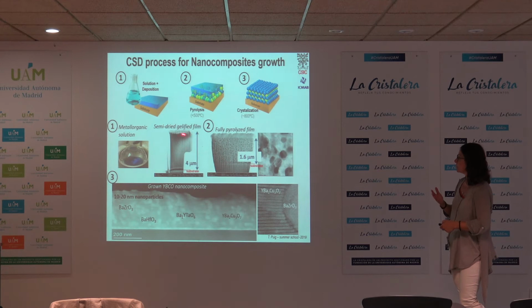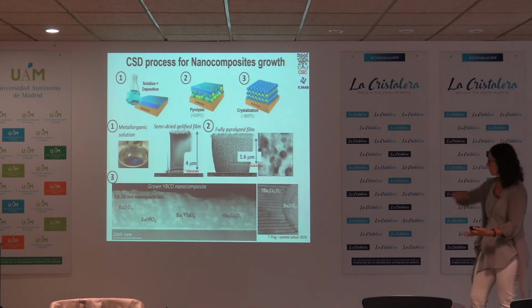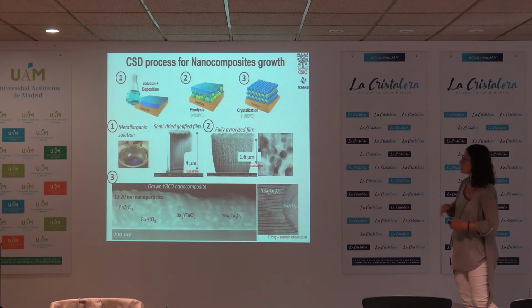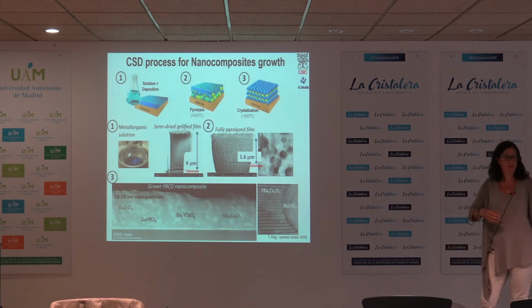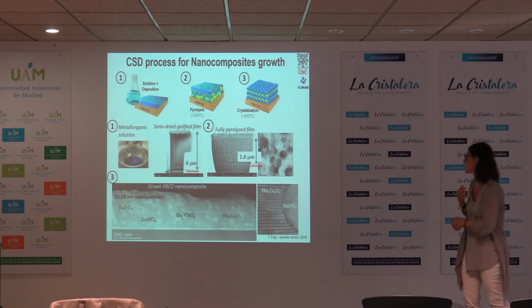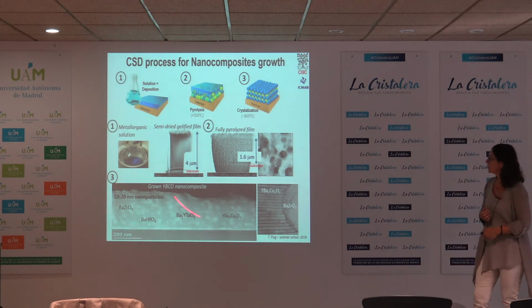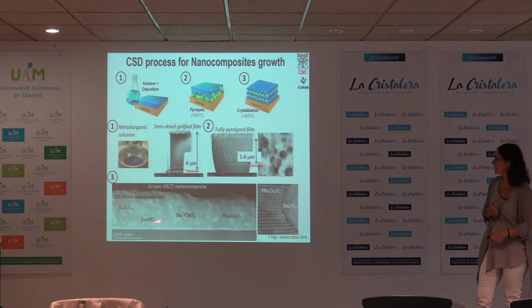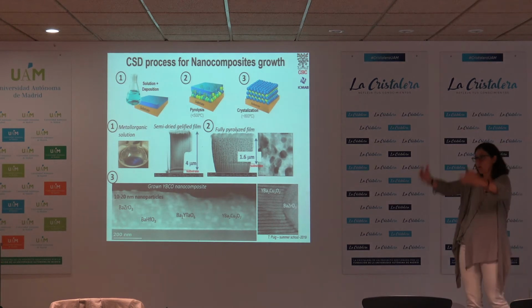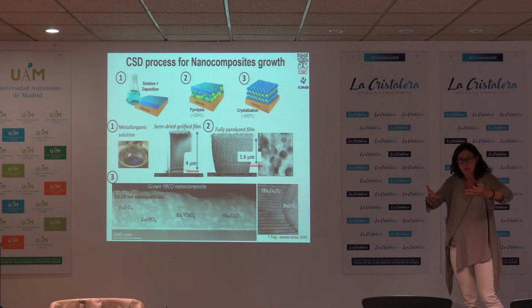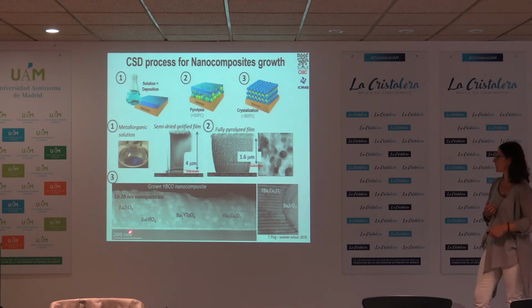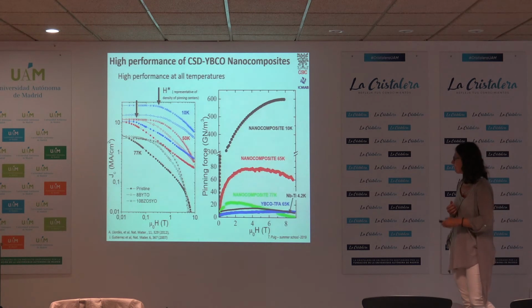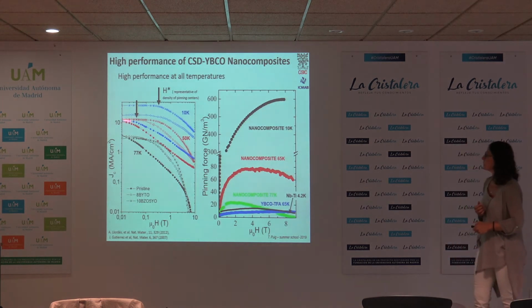So you deposit, you have a gel, you have to decompose this gel, you end up with nanoparticles of yttrium oxide, copper oxide, barium fluoride in this case, and afterwards you put it in another furnace, at higher temperatures, in the phase diagram region where YBCO will epitaxially grow, and then you get YBCO with the nanoparticles segregated. In this case, we also see that if we compare the sample without nanoparticles with the sample with nanoparticles, we have much higher currents. Also, at much higher fields, we have higher currents.